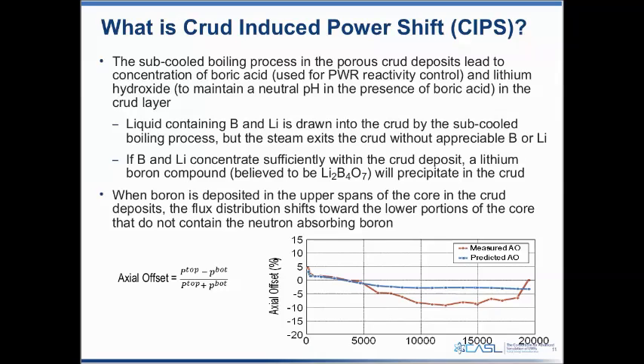that provides a way to concentrate boron and lithium in the crud, because the steam exits the crud without taking appreciable boron or lithium with it. Boric acid has light volatility, not much, and lithium really isn't volatile at all. So that process concentrates boron and lithium in the porous crud layer. And if we concentrate it to high enough levels, we deposit a lithium-boron compound in the crud. Typically, we expect that to be a lithium tetraborate type compound there.